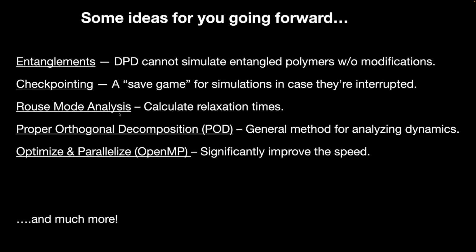You could implement Rouse mode analysis to calculate relaxation times. So you could study not only the structure of your polymers, whether they're in solution or in the melt, but you could study their relaxation dynamics. So you could see whether or not the Zimm model applies to your polymer solutions, whether or not the Rouse model applies to your polymer melts, your unentangled polymer melts. I've done this before with DPD, and it turns out that yes, it does agree with those. The dynamics do agree with those classical theories.